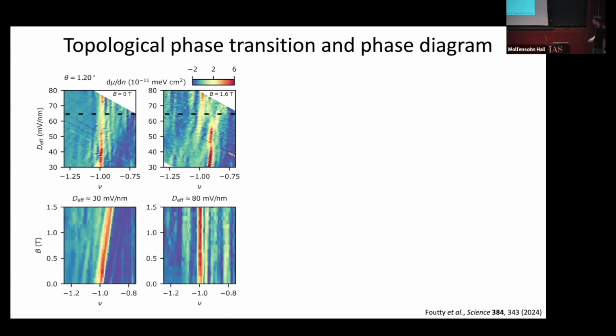And finally, we can do one better. We can look in the high displacement field limit and in the low displacement field limit as a function of magnetic field. And in the low displacement field case, you can see that this state is really sloped all the way down to zero magnetic field. So this is a quantum anomalous Hall insulator. In the high displacement field case, it's just vertical.